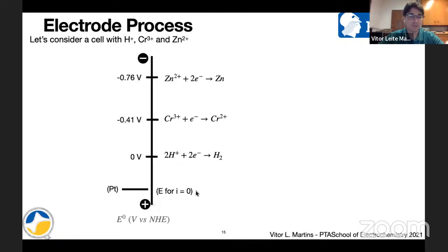Then we start applying a negative potential. So we are increasing the energy level of the electrodes. Remember that applying a negative potential is to increase the energy level of the electrons in the electrode. So we go through zero, and then this reaction will occur at the electrode surface. So you have reduction of protons to hydrogen at the platinum electrode surface.